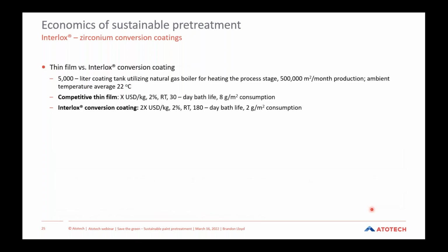And then lastly, if we consider an applicator that is transitioning from a thin film pretreatment to Interlox, we can see that again, the operating conditions are still quite the same. If we look at the comparisons of the competitive thin film versus Interlox, we consider here that the unit price will be about 2 times higher.